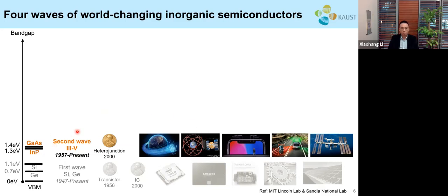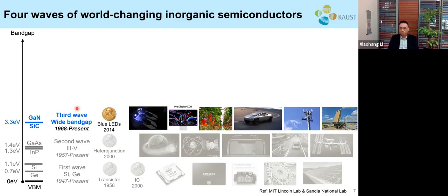The third wave of semiconductor is the so-called wide bandgap semiconductor, represented by gallium nitride and silicon carbide. They have a larger bandgap, about 3.3 electron volts. This larger bandgap allows them to have a larger breakdown field, and therefore they can handle power at very high voltage.